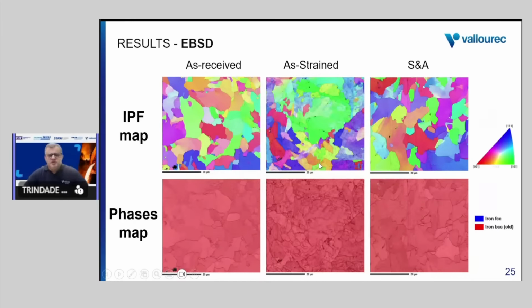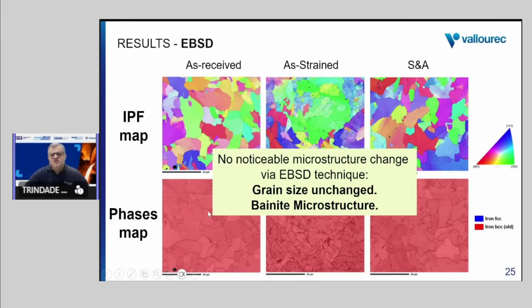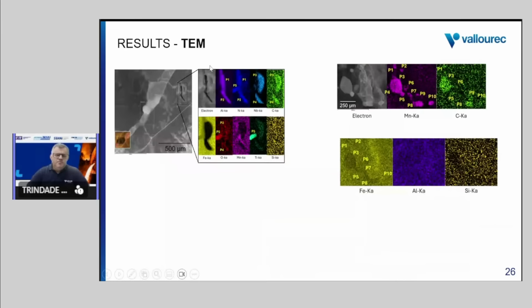If we use another advanced technique like EBSD, we can also confirm that there is no change in the grain size of the material, and also no change in the bainite microstructure, as already observed in the simpler SEM observation. And then if we want to go into more detail in the microstructure and observe the micro precipitates, we need to go further with an advanced technique, which we use here: TEM, transmission electron microscope.